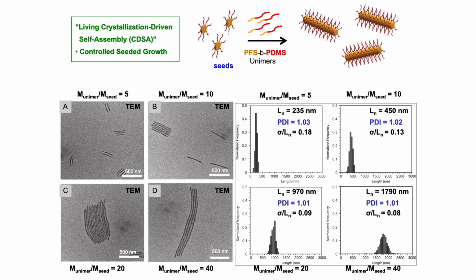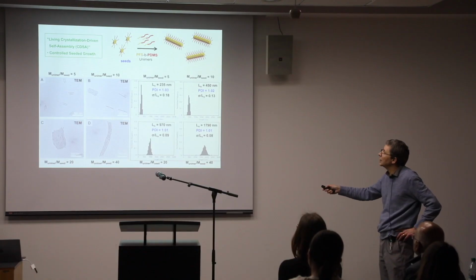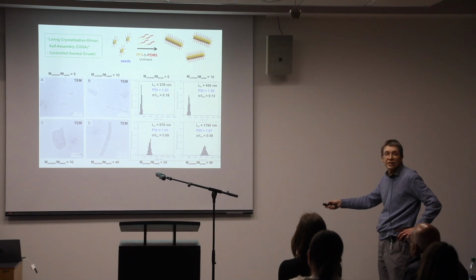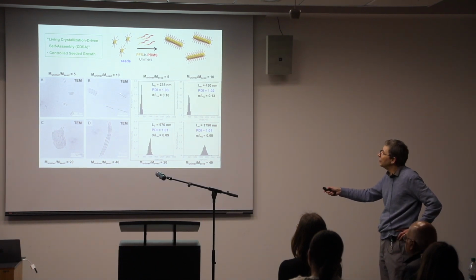This is illustrated here. This is the ratio of polymer we add to the seeds: here is 5, here is 10, here is 20, here is 40. You can see the fibers grow in a very controlled way, making uniform or monodisperse samples. This is the length distribution, a very narrow distribution, and you control the length here.